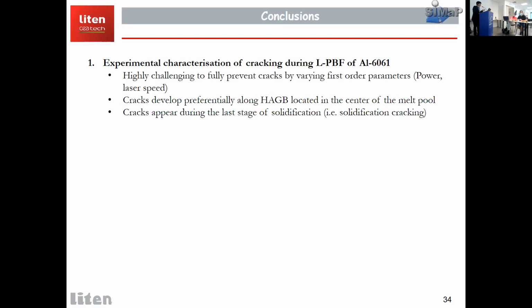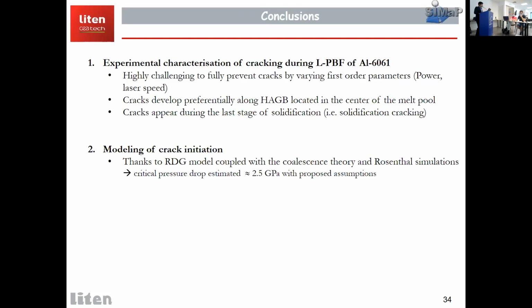Cracking also had a particular mechanism, which is the solidification cracking, occurring in the last stage of solidification. Based on our modeling work of the crack initiation, thanks to the RDG model coupled with the coalescence theory and the Rosenthal simulations, we were able to estimate a particular critical pressure drop, which is around 2.5 gigapascal, above which cracking is quite sensitive.